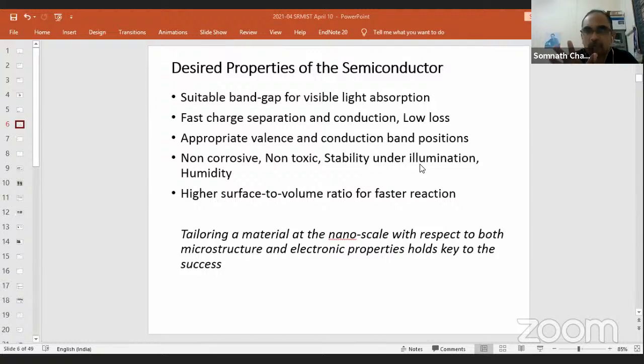We don't talk much about IR absorption because IR also has a long-term problem: heating in the sample can degrade the material. Of course, if you can absorb IR without any degradation of the sample, that is the best. That happens in silicon. That is why silicon has a 1.1 electron volt band gap. It actually absorbs the entire spectrum. But generally we want visible light absorption. Visible light absorption means the band gap of your material should be up to around 2 or 2.1 electron volts. Next, fast charge separation and conduction, with low loss.